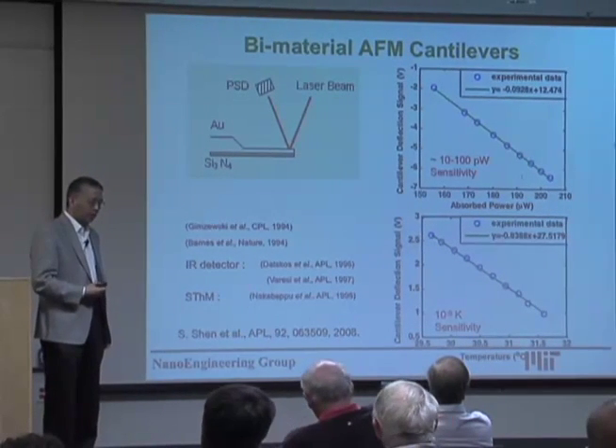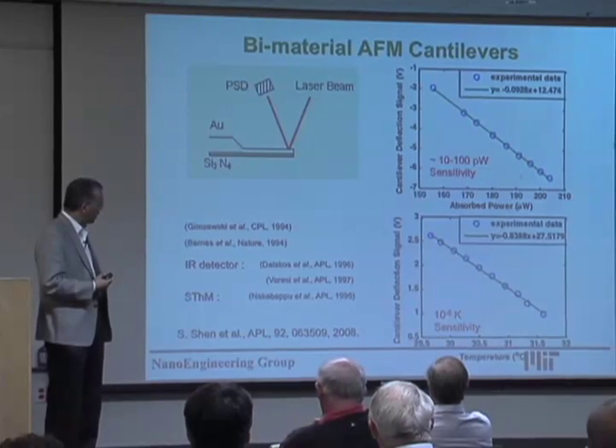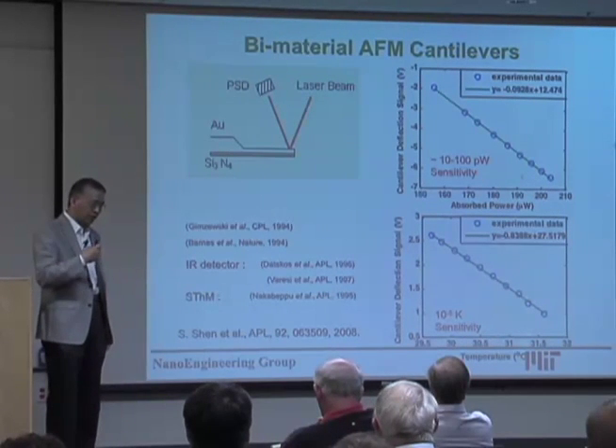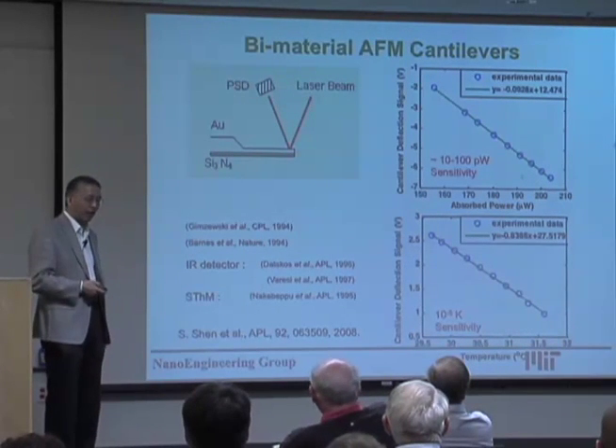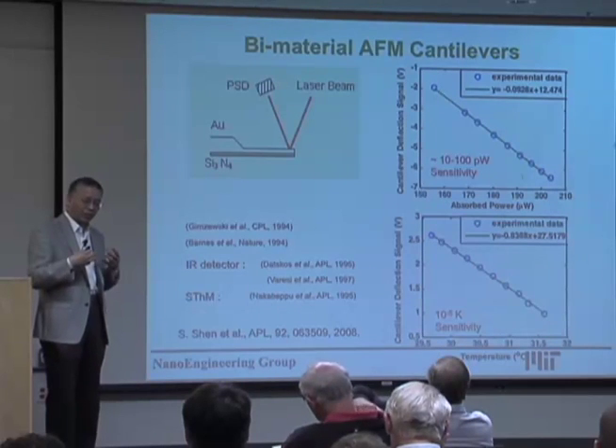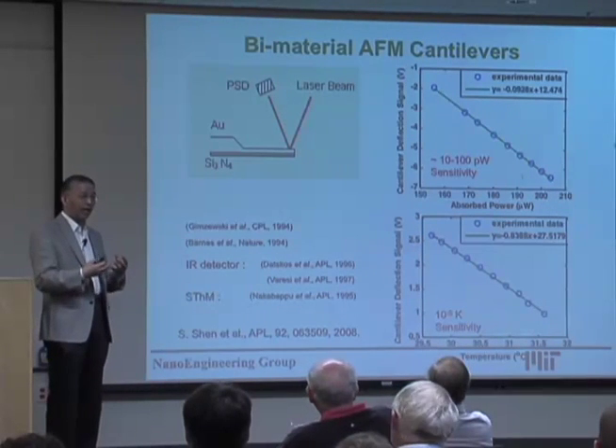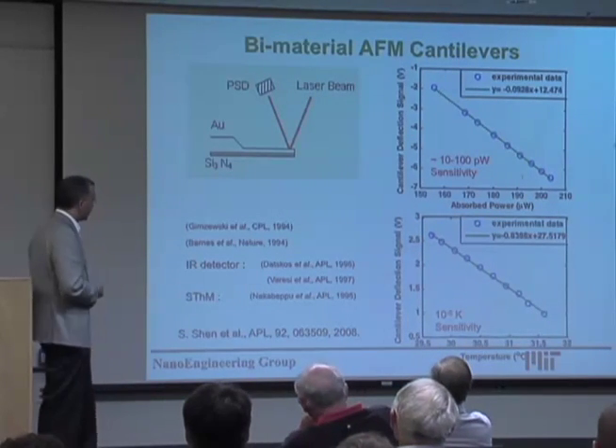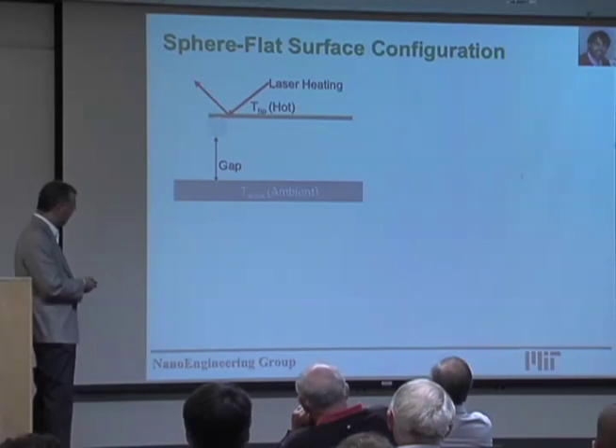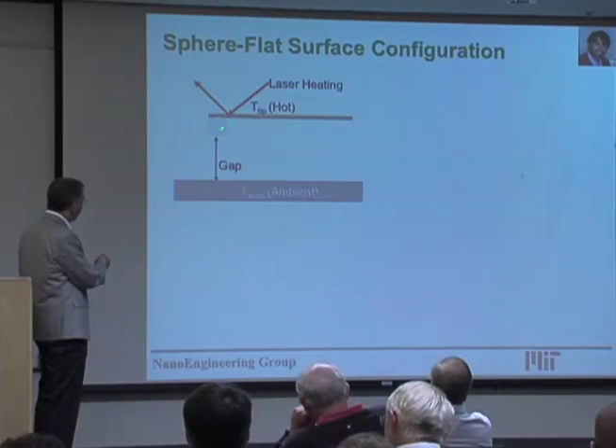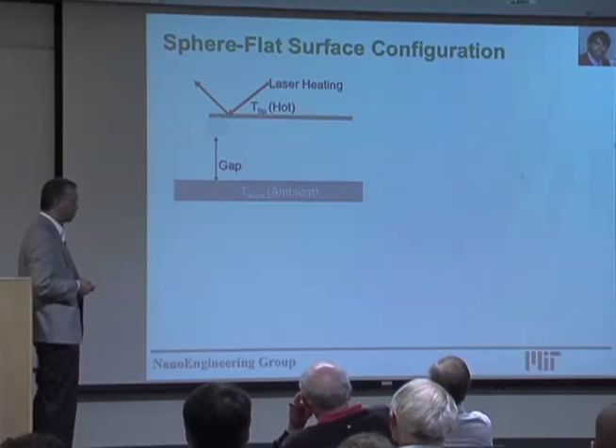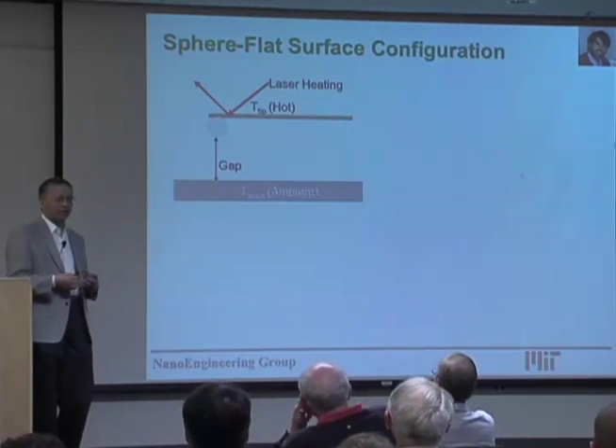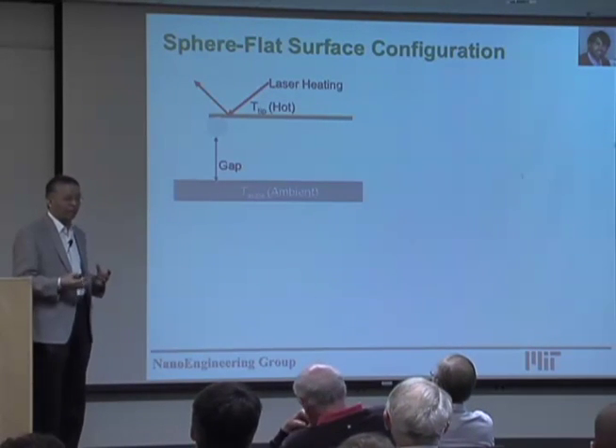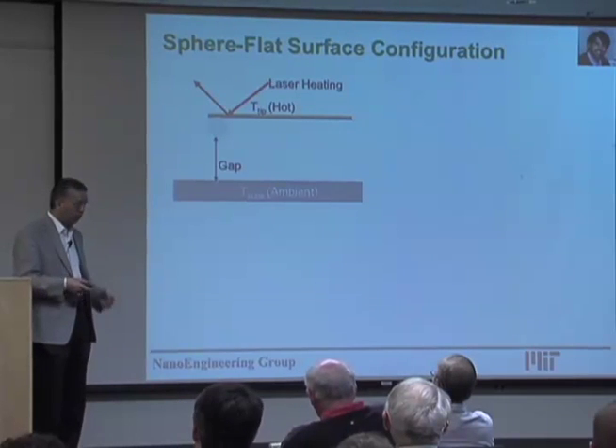At the time we measured our cantilever, it could have tens of picowatt sensitivity and millikelvin temperature sensitivity. So using that, we said, okay, let's glue a sphere onto the cantilever, and we can use this as a heat flux meter and measure the heat flow between the sphere on the cantilever and a flat plate. The first thing we did is the same as a normal AFM cantilever. We glue a sphere, and